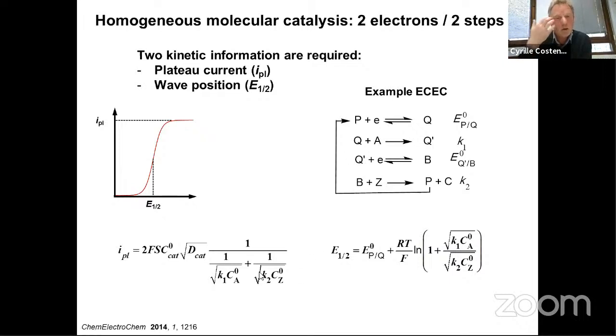And so by a combination of the position of the wave and the plateau current, you can actually extract the 2 rate constants here. And of course, if you have a substrate and a co-substrate, you can play around a little bit with the concentrations to push the system in a situation where one is rate determining or the other one is rate determining. So to make the situation clear, we have the tools to analyze 2 electron, 2-step processes.